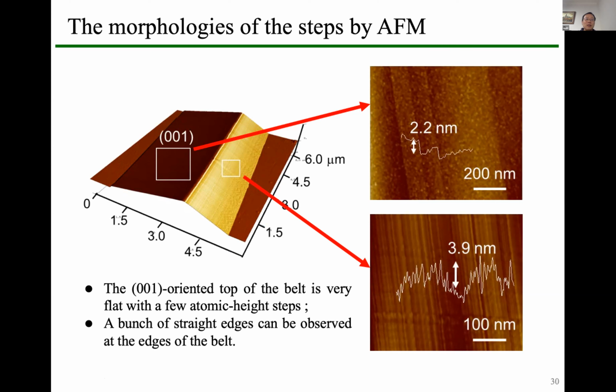In principle, if the structures are the same, then here and here should be the same, but actually here is stronger. But that is not edge, that is side surface. Experimentally, if you prepare a wire, you have a top surface and the side surface. On the top surface, you have very few edges, but on the side surface, you have a lot of edges. The only difference between the top and the side is the density of edges. So that means you have a direct link between these.